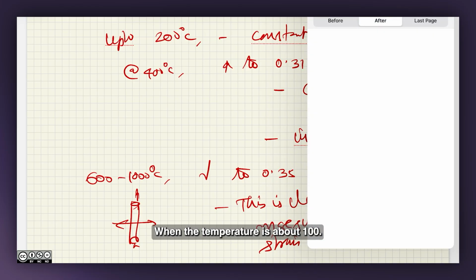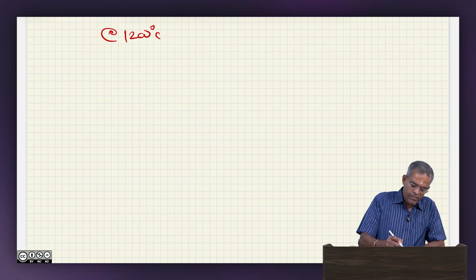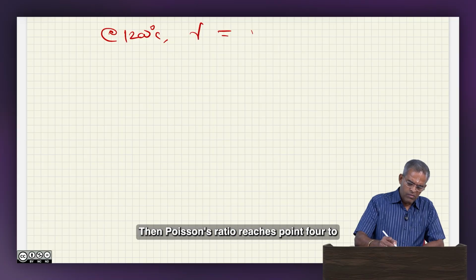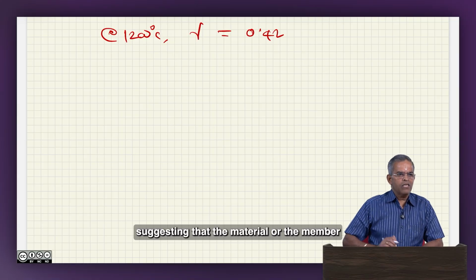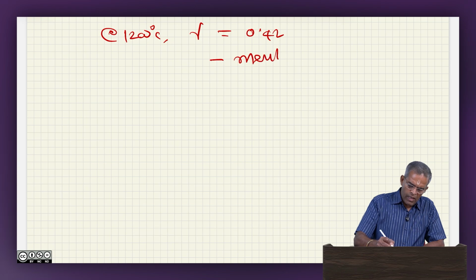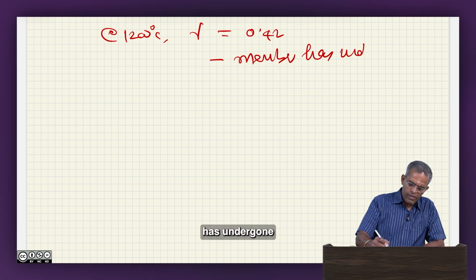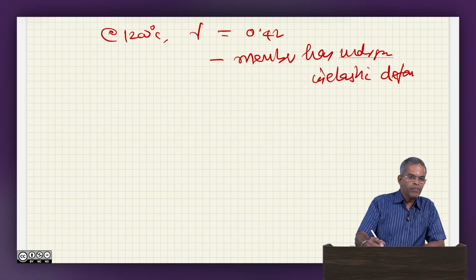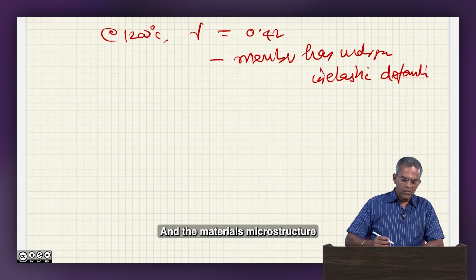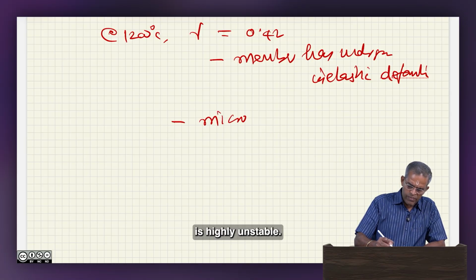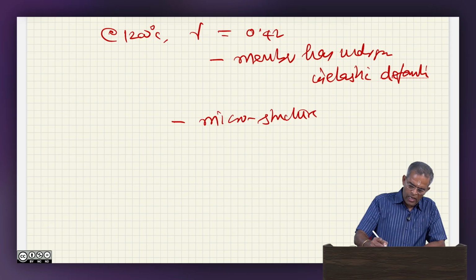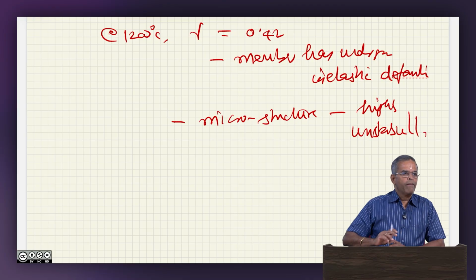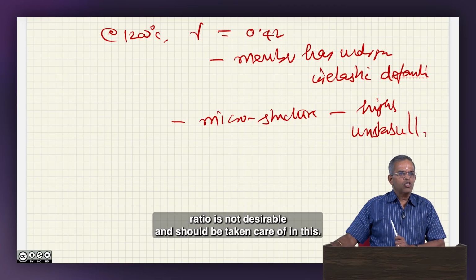So, this is a very undesirable and unexpected design situation. When the temperature is about 120, then Poisson's ratio reaches 0.42, suggesting that the material or the member has undergone inelastic deformation, and the material's microstructure has become highly unstable. Therefore, such a rise in Poisson's ratio is not desirable and should be taken care of.